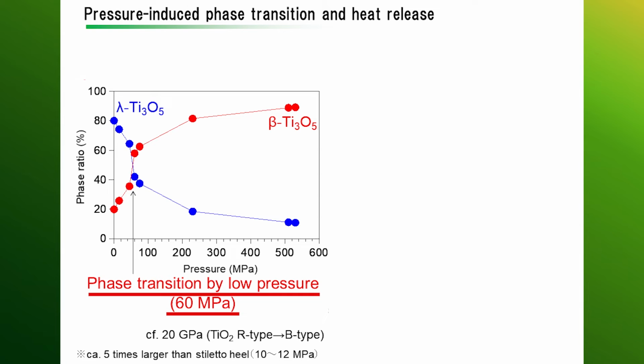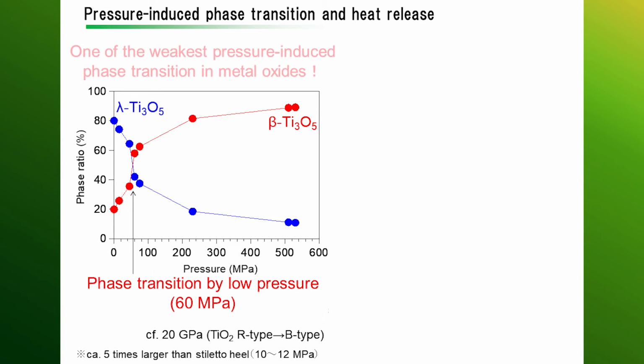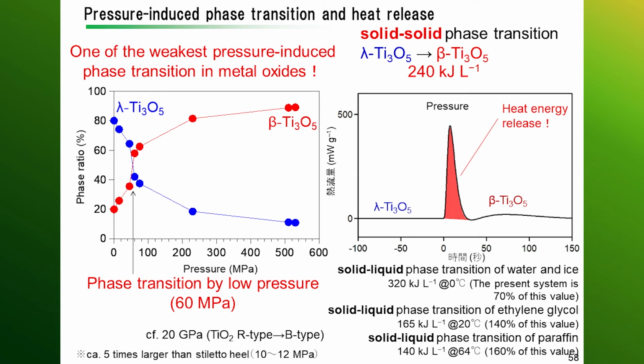Now you may think 600 is large, but this is an oxide. It's a ceramic. And thinking about ceramics, thinking about 60 megapascals, the pressure of a stiletto heel is said to be 10 to 12 megapascals. So if you step down hard with a stiletto heel, that will cause the transition. This is an oxide material that undergoes a phase transition at the lowest possible pressure.